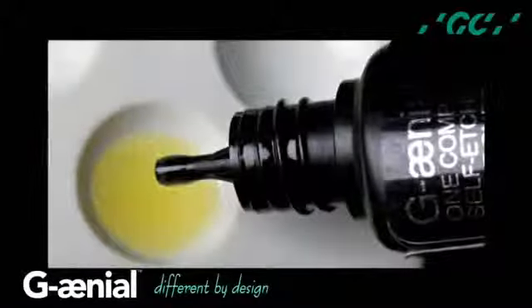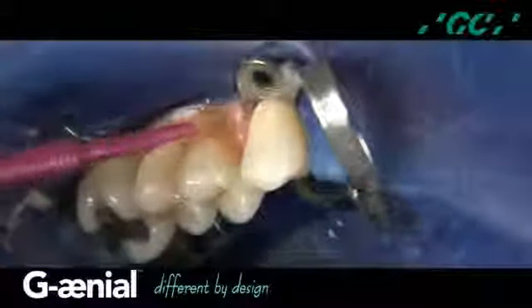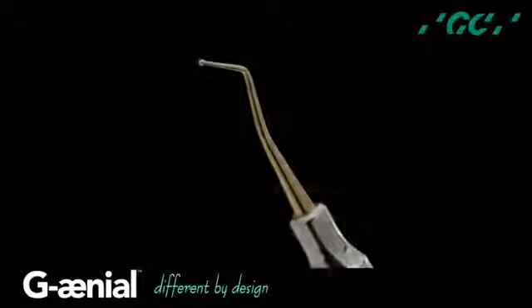A self-etch adhesive, Genial Bond, is applied to the enamel and dentin of each preparation with an applicator tip, allowed to dwell for 10 seconds, air dried with an ADEC warm air tooth dryer for 5 seconds, and light cured for 10 seconds. The initial layer of A1 shaded Genial Universal Flow is applied to the axial wall of the preparations with a syringe tip and uniformly distributed and adapted with a round-tipped instrument, an M1 by American Eagle, and light cured for 10 seconds.